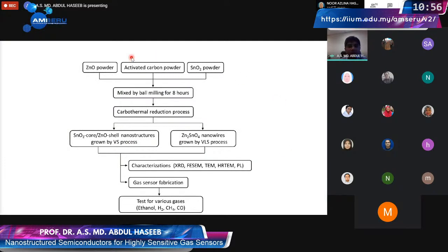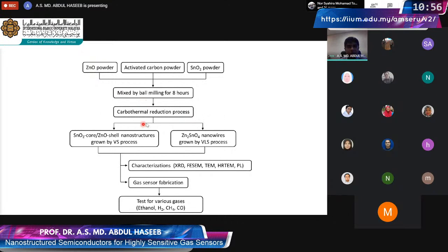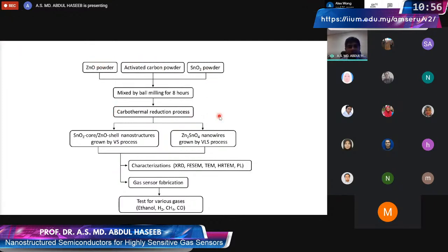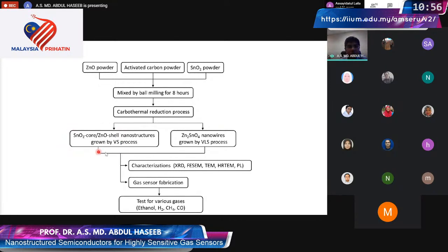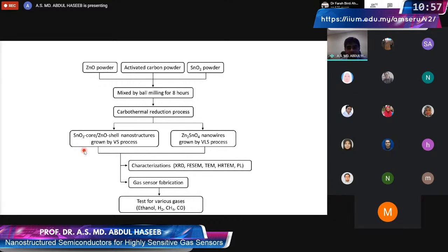So what we did here is rather straightforward. We collect commercial zinc oxide powder and tin oxide powder. We mix them with, again, commercial activated carbon, ball mill them to mix them together, and then we heat them. This is the so-called carbothermal reduction process. Carbon reduces the zinc oxide and tin oxide in this process. And then after this reduction, we have a vapor. The vapor then condenses, and in the condensed form, they reoxidize, and we have different types of structure. This is a very interesting system. We can have many different types of nanostructures formed. We formed nanostructures by the vapor solid process, and we could also grow nanostructures by the vapor liquid solid process, depending on the place where we grow them inside the chamber.